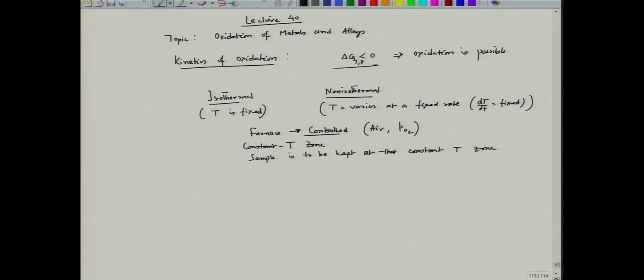Fine. And now we will measure, what are the measurement parameters? Delta W is the weight change from the initial weight. Let us say initial is W0, and then the weight after oxidation is W. Then the weight change becomes delta W. Since the oxidation is basically a reaction between metal with oxygen at the surface, now in order to avoid differential areas of the same sample exposed to a particular temperature and having difference in weight gain,